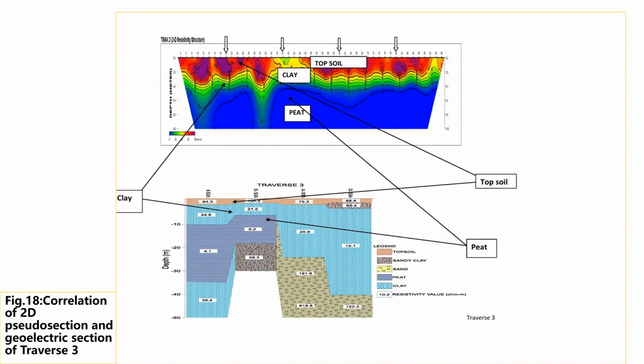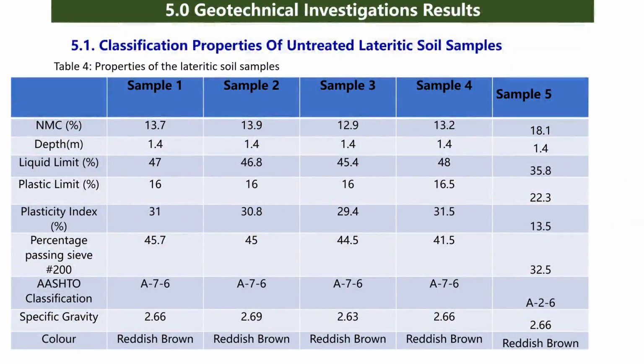This table is showing the classification properties of untreated lateritic soil samples. From this table, you can see that the percentage passing through sieve 200 of sample 5 only has a percentage that is below 35%, which is the limit recommended by the Federal Ministry of Works and Housing for a good soil to be used as subgrade soil for road construction. Samples 1 to 4 have percentages that are higher than 35%.